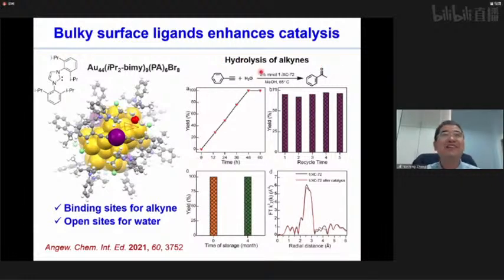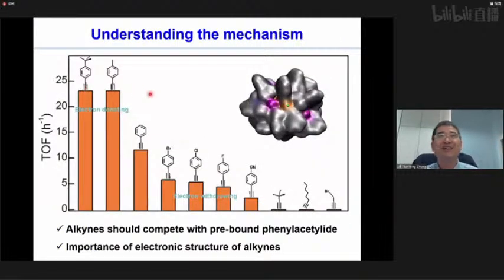Okay, and as you can see here, we don't see a decrease in activity, and the catalyst can be used so many times, just because we have these surface binding sites. If we don't have this bulky carbene, we don't have this activity at all, because we don't have the open surface sites for water. So the solution of this structure gives us a really clear image of how the catalysis is taking place on the surface. And more importantly, with this kind of model catalyst, we can understand how the electronic structures of the reactants influence their catalysis. For example, for alkynes with alkyl groups, there is no activity at all because the binding site is not good for this alkyne.